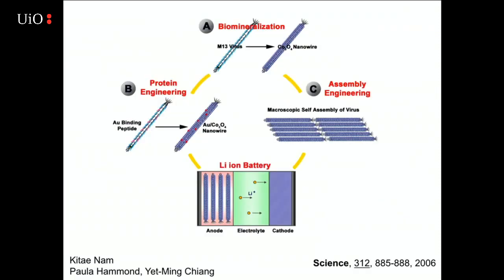To make the first kind of virus batteries, what we did was take a virus, and we selected for the ability to grow cobalt oxide nanoparticles. These nanowires will naturally self-assemble based on their anisotropic shape. And then we actually go in and we do additional engineering. So if you start with the ability to grow a material of interest, in this case it's cobalt oxide, if you're able to grow it but you want to improve it, you can either go through additional genetic engineering or you can do protein engineering to add other kinds of groups.